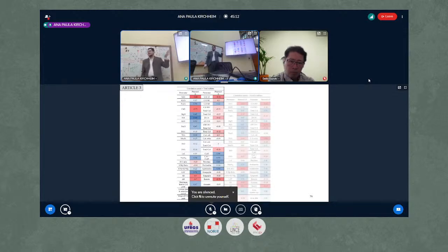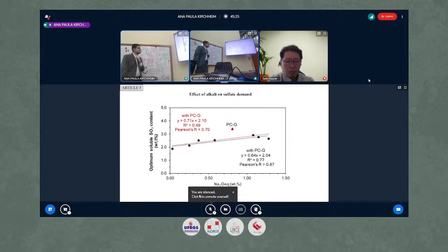So here, what I did, I calculated the sulfate coming from gypsum and the sulfate present as alkali sulfate. So I disregarded the sulfates incorporated in alite and belite. And I ran this analysis again, and now I see better correlations, but first, not with C3S and C3A. This also was not good enough, but I saw a good correlation with alkali. Again, the exception is PCG, I will explain later why, but we see a great correlation.